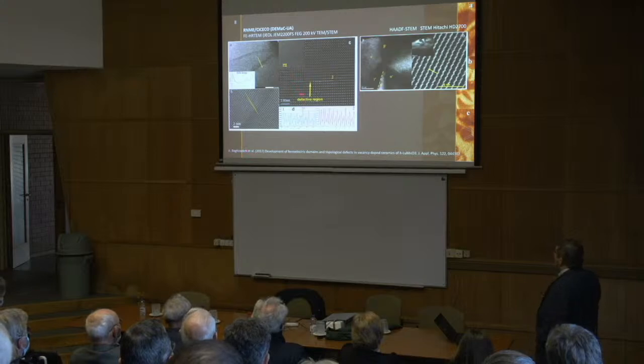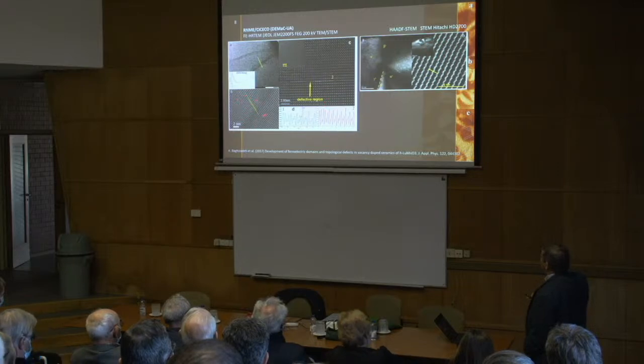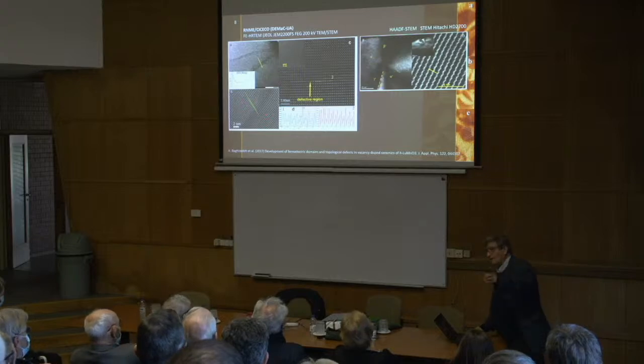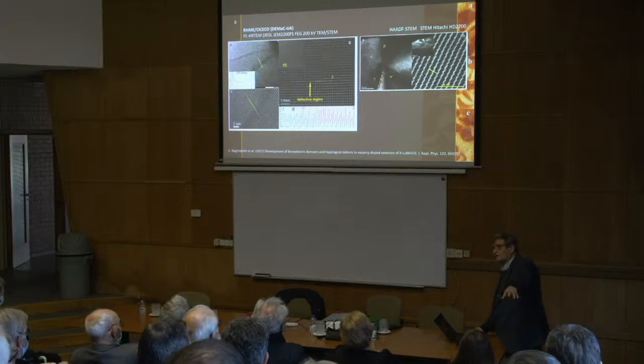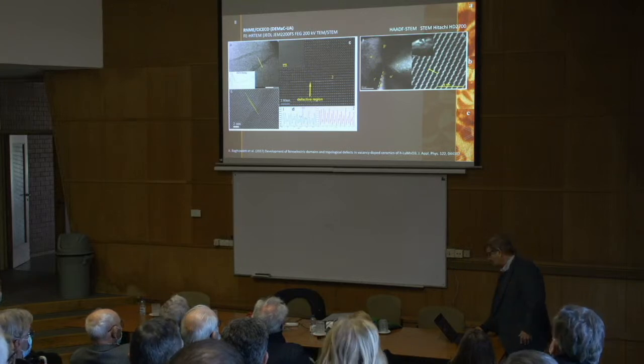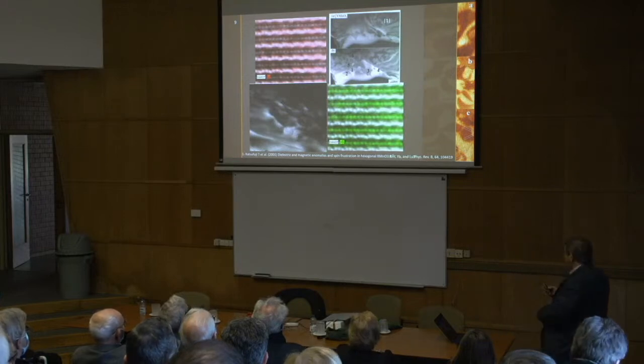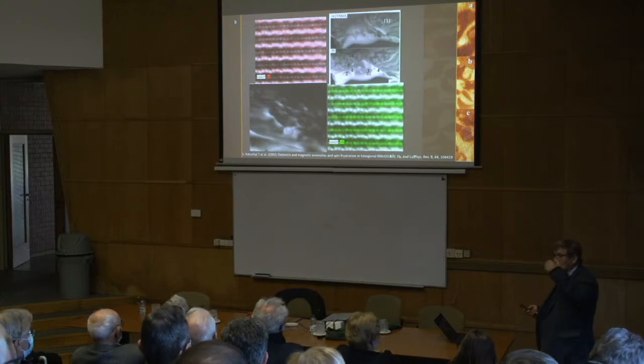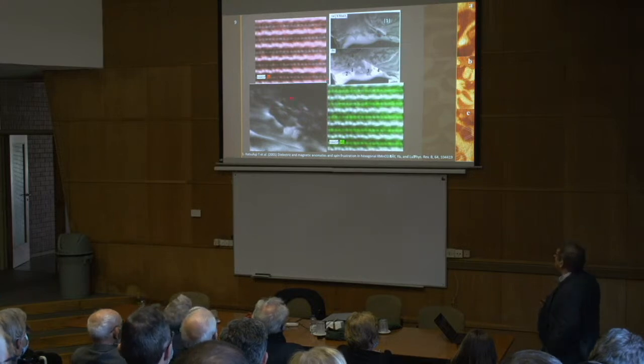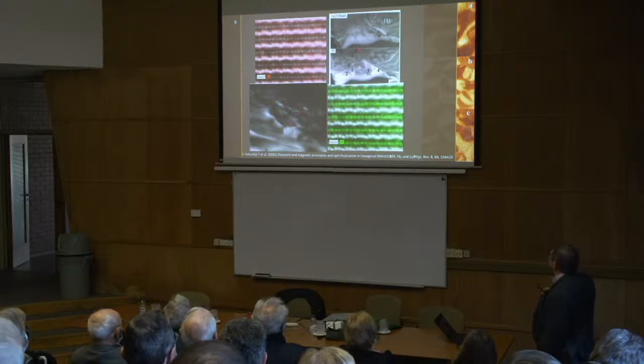So we were able to see, okay, this is our lattice. Here and there we could see effects of the polarity in the TEM image, but what happened to the effects of the crystals? We are working not with single crystals, but with ceramics, which puts grain size, impurity, and strain constraints on the samples. And our frustration, not of humanities, but our frustration in research, was, okay, this is what was published very early, 2001, but we can only get these eventual topological vortices, but okay, are they the best we could do?